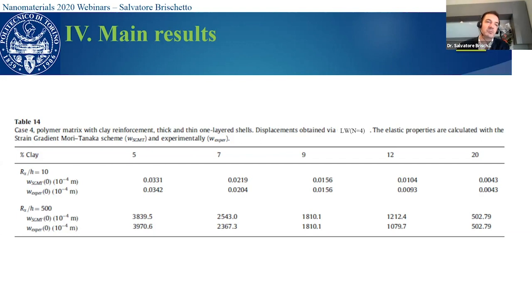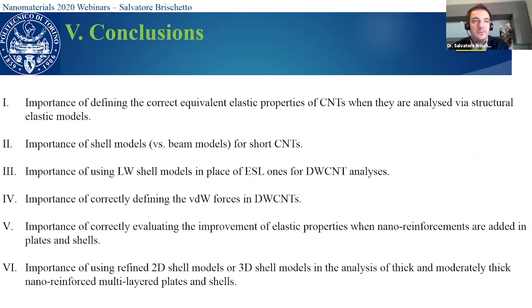If you include the transverse displacement obtained with the elastic properties from the Mori-Tanaka scheme, there are larger differences. So, in conclusion, we have seen the importance of defining the correct equivalent elastic properties for carbon nanotubes when they must be analyzed by means of structural elastic models. We have seen the importance of shell models for the analysis of short carbon nanotubes. We have seen the difference between a layer-wise approach and equivalent single layer approaches in the case of double-walled carbon nanotubes analysis, and in this case we also saw the effects of the van der Waals forces.